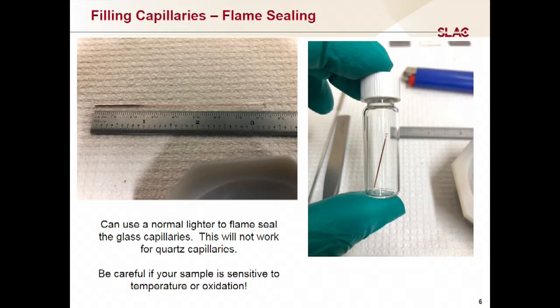And so now what I want to do is get rid of all of this part of the capillary. I don't need it, and I want to seal it somewhere in this area. And in this case, what I did is I flame sealed it. And all you do is take the lighter and move the capillary through the flame. It melts. The glass collapses on itself. It will seal. You take the other piece away, and you can see here the end result.